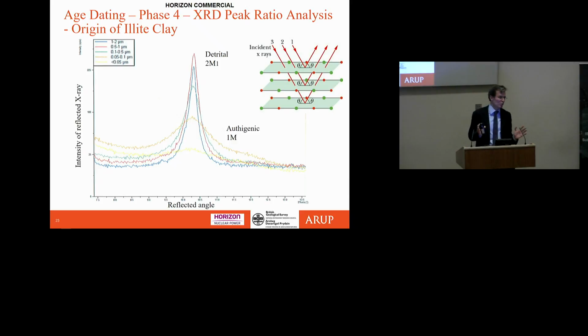And the simple story is that if you have an older clay particle and it's had a very long time to form, the crystal structure is well formed. So it's in nice layers, all organized, and the X-ray diffraction peak that comes back is therefore very narrow because it's all parallel, all aligned, well formed, because it's had a long geological history to do that. In this case, it was hundreds of millions of years. The clay particle is formed by metamorphism, and it gives that strong peak. And those are the detrital particles, the bits that have fallen off or been brought in from the wall rock, the old stuff. And it gets referred to as 2M1 crystal structure, but that's clear that that's a detrital particle and it's old because the lattice is well formed.